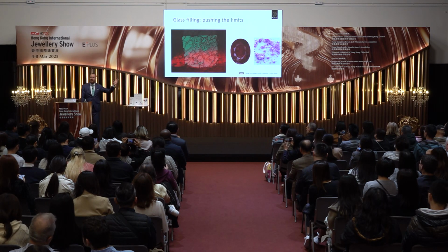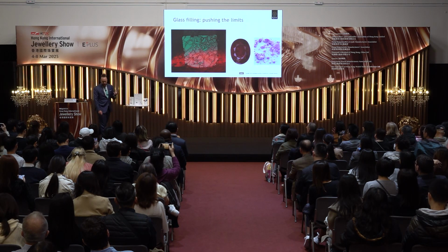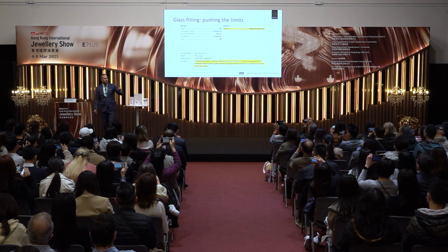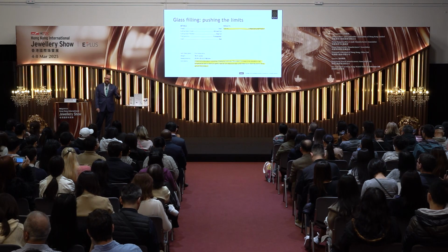Now, obviously, when a material like this comes through the GIA laboratory, we will no longer call it a natural ruby. A piece like this that would just crumble if you take the glass out would get called a manufactured product. And it comes with a disclaimer that this is a product that consists of ruby and lead glass, where these two things are mixed together and later faceted. So you can push it so far that these things actually become a manufactured product and are no longer considered a natural ruby with treatment. They become a manufactured product.